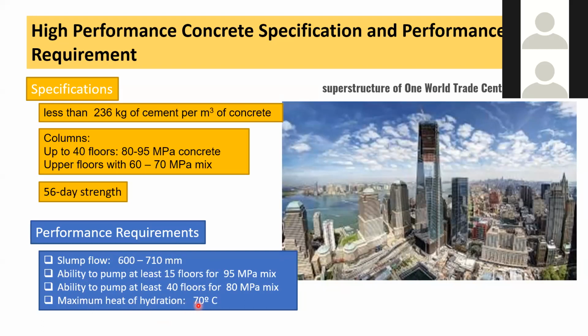And it was also specced out that the maximum heat of hydration could not exceed 70 degrees Celsius. So now these are all performance requirements. This is what is expected from concrete that comes to the site, in addition to our strength. So the strength requirement is anyway there, but these are the additional requirements. And if you look at this performance requirement in the blue box here, these are fresh concrete performance requirements, and these were placed as requirements on the contractor who supplied the concrete. Now, for this requirement, the cement could not exceed 236 kgs, and that was done in order to reduce the carbon footprint and have a greener concrete.